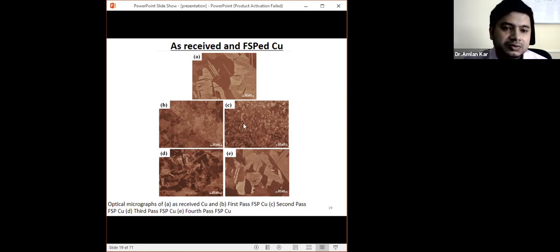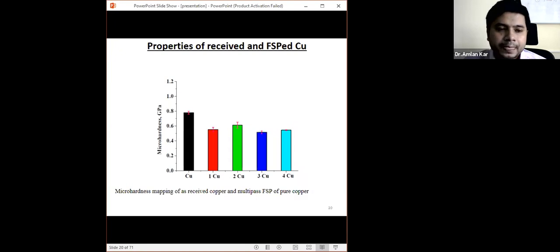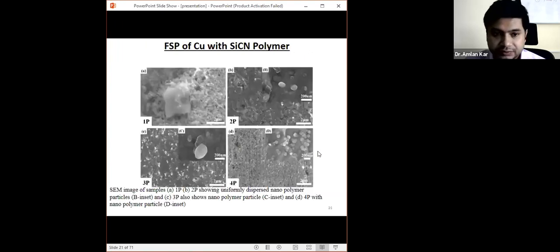After the deformation, you can see there is a substantial amount of grain refinement. But if you add additional processing, additional friction stir processing, there is an increase in the grain size due to the higher heat input. Therefore, it is important to have process optimization. You can see the microhardness: since the grain size increases after the fourth pass, there is a reduction in the microhardness.